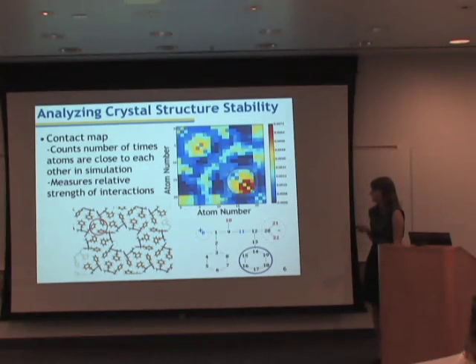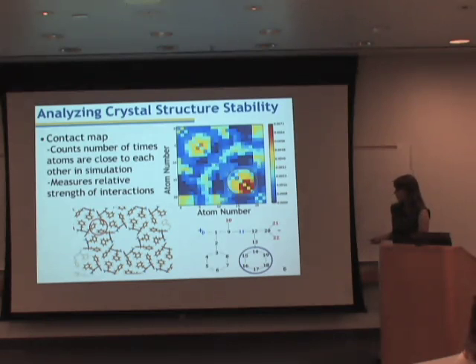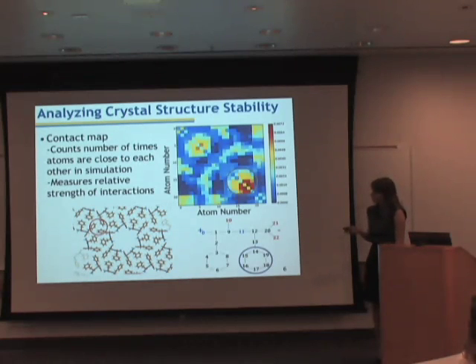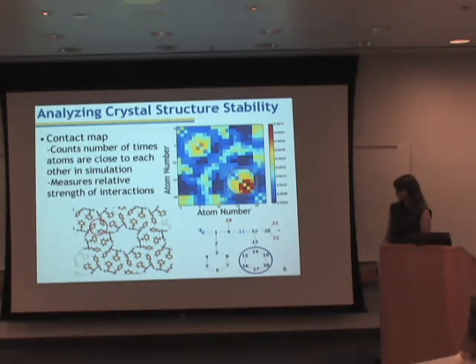Rather, the strongest degree of interaction is seen here, which corresponds to these so-called second rings on the peptides. Looking at the crystal structure, it's actually not particularly surprising that these are the strongest interactions, as these rings come together in groups of 3, as is circled on this diagram of the crystal structure on the left.